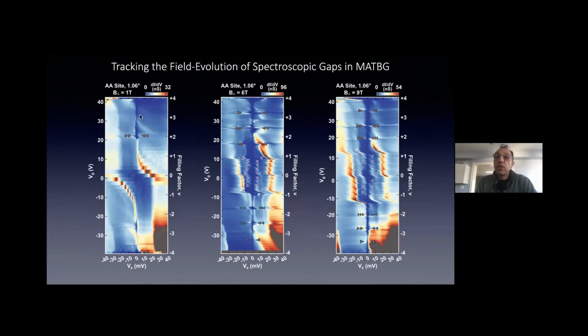So I go back to what I showed you before. This was at the very low temperatures. These are the spectra. You see some gaps at low fields. Then you turn up the field. And this is a very rich system. It has a Dirac point, so you could have a zero Landau level. But what you can see by eye is there are lots of gaps opening up in the system as you apply a magnetic field. And you notice that these gaps appear at some gate voltages, and these gate voltages, corresponding to some density, move as you change the value of the magnetic field.